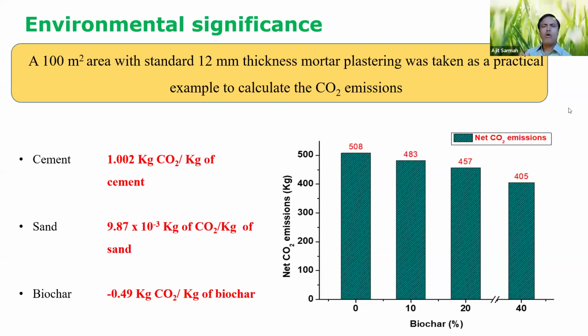So we wanted to find out, okay, we can use biochar in place of cement or sand. Does it tell us anything? How can you find out what is the net carbon dioxide emissions if we add biochar in the mortar or concrete? So what we did, we took an example. We assumed that we have 100 square meter area, 10 meter by 10 meter. It's like a big wall. It has got a standard thickness of about 1.2 centimeters or 12 millimeter thickness. It's basically a wall with 100 square meter area with thickness 12 millimeter, standard mortar plastering.